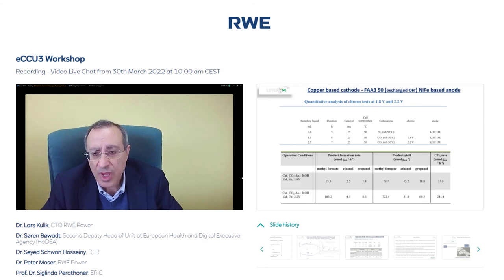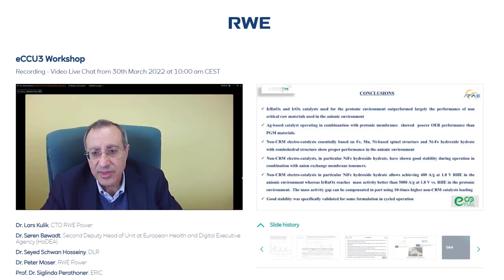Slide number 18, please. We have estimated quantitatively the carbon dioxide conversion into liquid carbonaceous products corresponding to 240 micromoles per gram per hour. And this, of course, needs to be significantly enhanced by improving electrode and catalyst structure at the cathode. However, moving to slide number 19, dealing with the conclusions, we have developed and characterized different anode electrocatalysts for the oxygen evolution reaction. We have observed several promising formulations based on spinel structure, nickel manganese, nickel iron, but also the nickel iron hydroxide hydrate with rhombohedral structure.